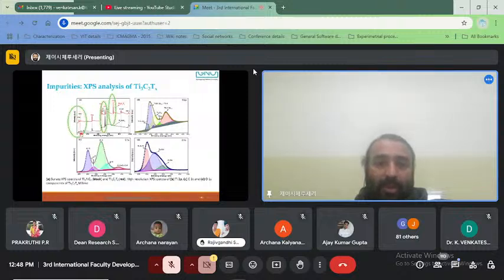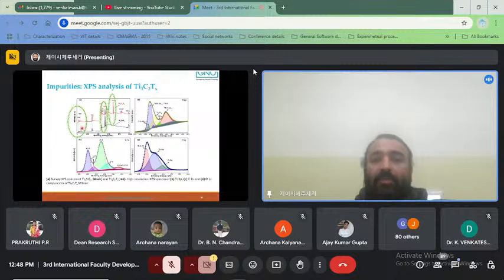Also important is aluminum. We say selective removal of aluminum from the MAX phase, but in reality, not all the aluminum gets removed. There will always be some amount of aluminum present, but our target should be to minimize it, so there should not be major aluminum. That means the MAX phase has not changed into a MXene. So this XPS analysis is a very good surface analysis technique to know not only the composition and the structure, but also the terminal groups.